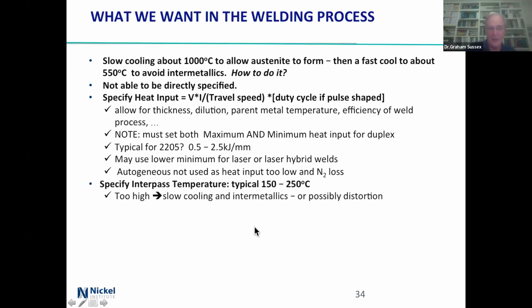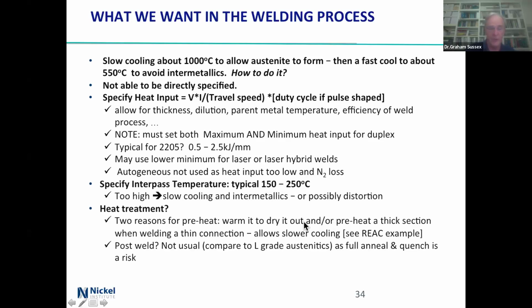Specifically, let's look at the interpass temperature. Typically, you're looking at about 150 to 250. And yes, I know they vary a bit. If it's too high, then slow cooling and intermetallics, maybe distortion if you really cook it. And what do you do? Well, heat treatment. Yeah, you might preheat it, but really it's only just to warm it and dry it out. Or if you're talking about a really thick section, yes, okay, you may have to preheat it. I'll talk about that in a moment when we talk about this REAC example.